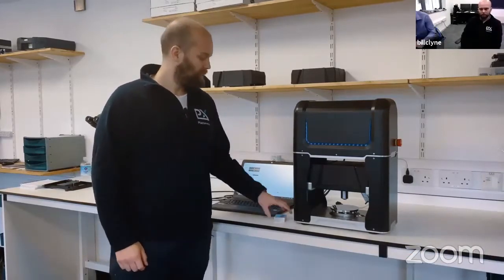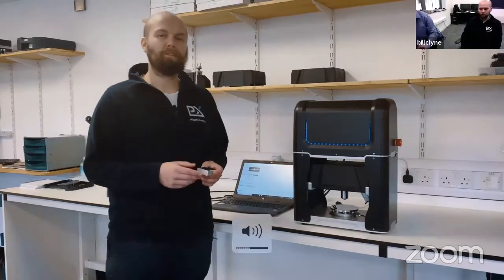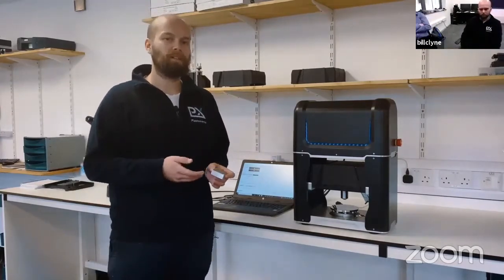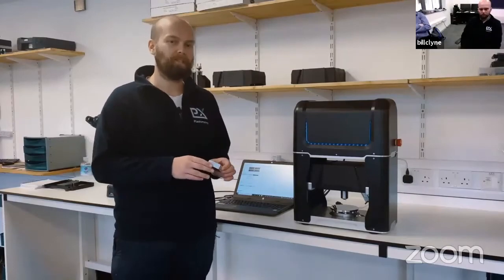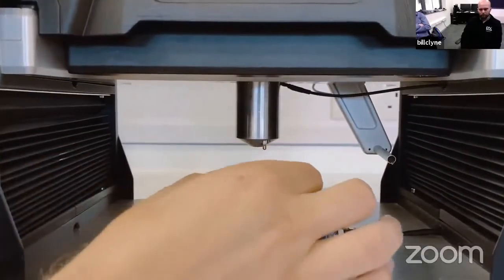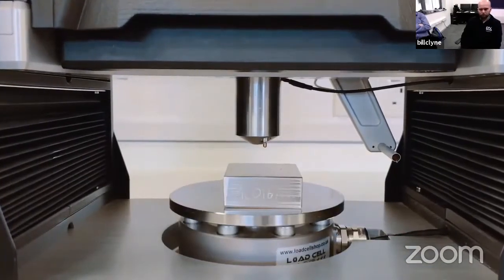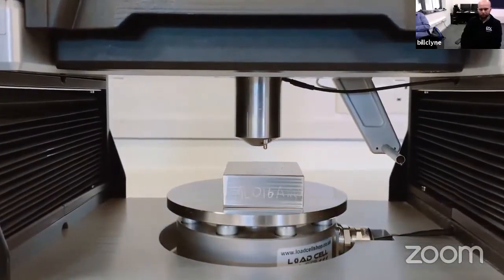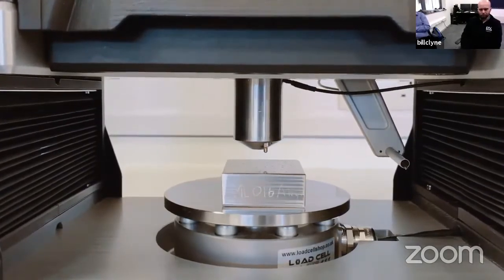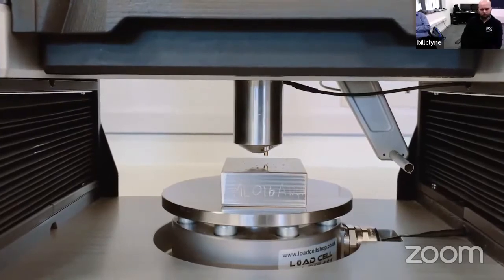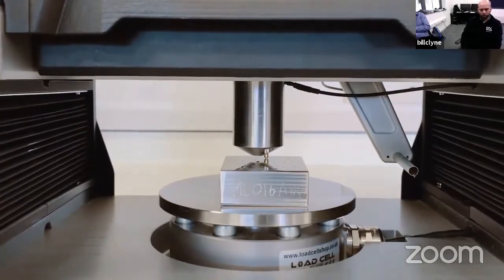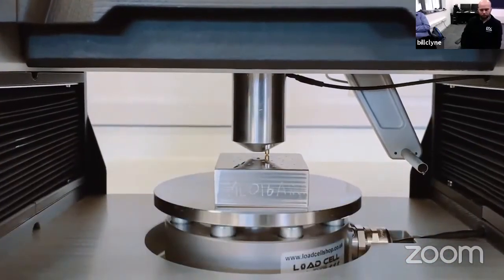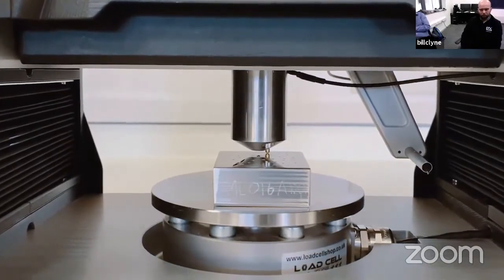Welcome to Plastometrex. This is one of our indentation plastometers. And today, I'm going to show you just how simple the workflow is. Here, we have some aluminium plate, and for sample preparation, we've done a quick surface grind, and we've ensured that we've got a flat surface for indentation. To run a test, place the sample underneath the indenter head. Once you click start, the indenter head will come down, and the LVDT will come into contact with the sample surface, and the indenter head will pause. This allows you to make any fine adjustment to the position of your sample for the test. Once that's complete, everything from this point on is automated.